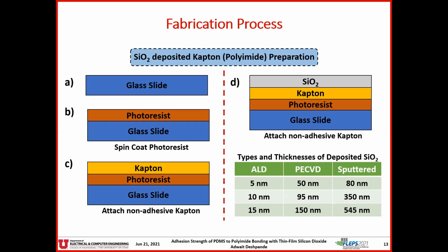SiO2 was then deposited on top of Kapton using one of three methods: atomic layer deposition, plasma enhanced chemical vapor deposition, and sputter deposition. Three different thicknesses were deposited for each type. For ALD, those were 5, 10, and 15 nanometers. For PECVD, they were 50, 95, and 150 nanometers. And for sputtered SiO2, they were 80, 350, and 545 nanometers.